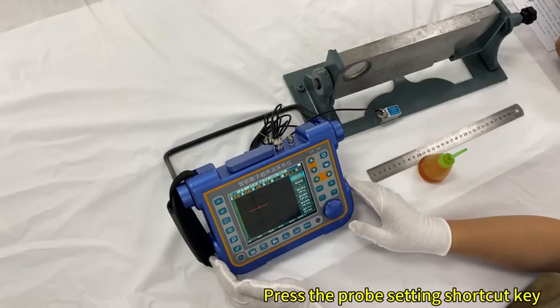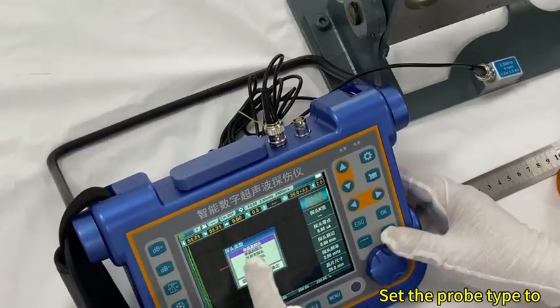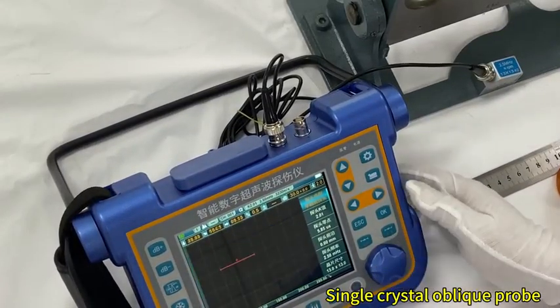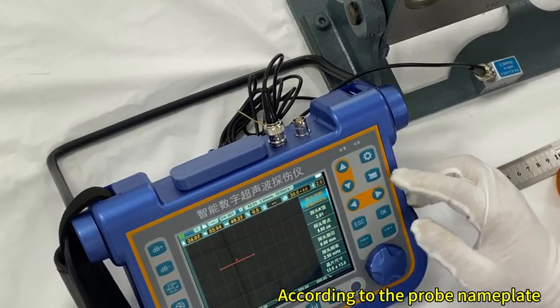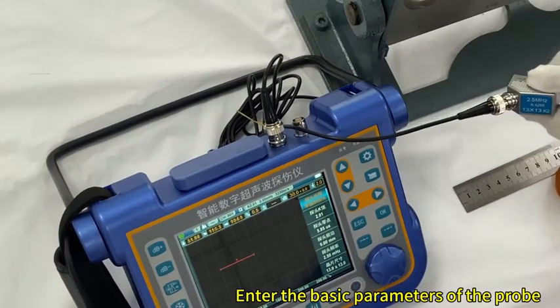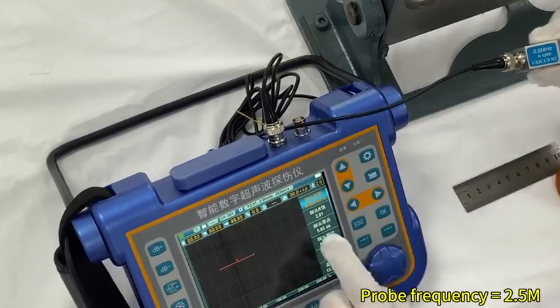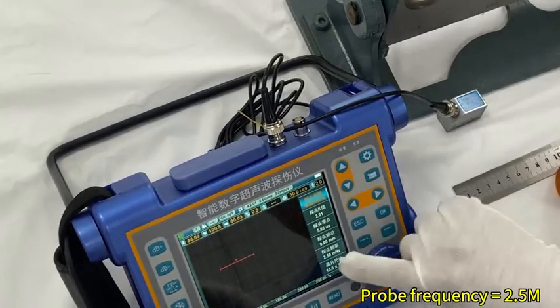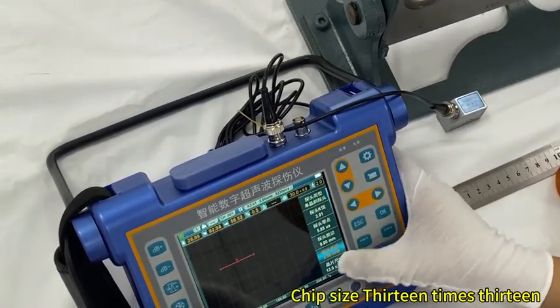Press the probe setting shortcut key. Set the probe type to single crystal oblique probe. According to the probe nameplate, enter the basic parameters of the probe. K value equal to 2. Probe frequency equal to 2.5 MHz. Chip size 13 times 13.